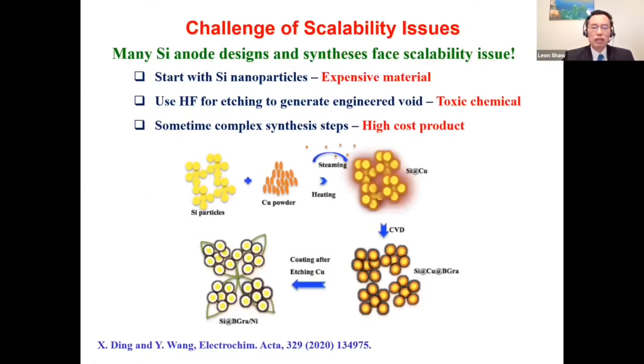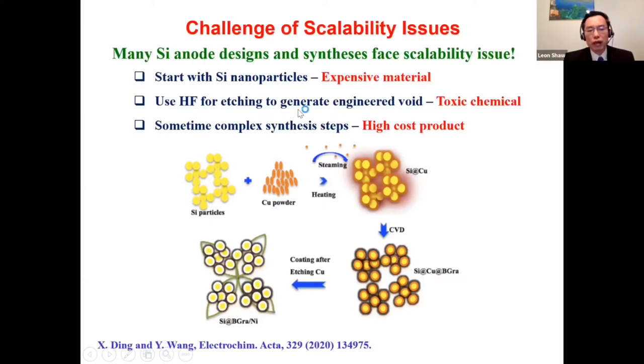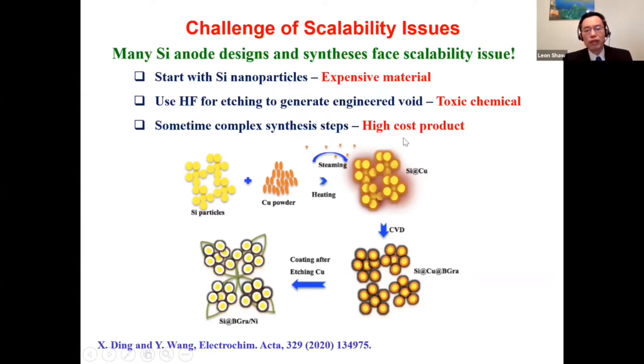However, many of these synthesis approaches face scalability issues. Specifically, many methods start with silicon nanoparticles, which are expensive starting materials. Furthermore, many synthesis techniques use HF to etch silicon dioxide and generate the engineered voids, and HF is a very toxic chemical. As a result, processes become very expensive to handle, and some have very complex synthesis steps leading to very high-cost products.